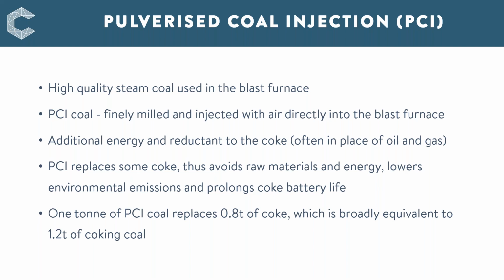The PCI coal is generally a low volatile bituminous steam coal with very high heating values. I've seen heating values of anything 7,000 to 7,800 kilocalories per kilogram published, versus say 3,300 to 6,700 kilocalories for a typical steam coal. A PCI coal will be very low in sulfur, so less than 0.5% sulfur content. It should have less than 10% low ash content.